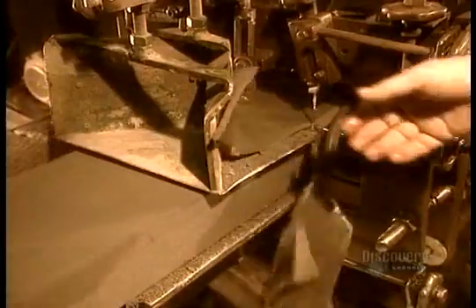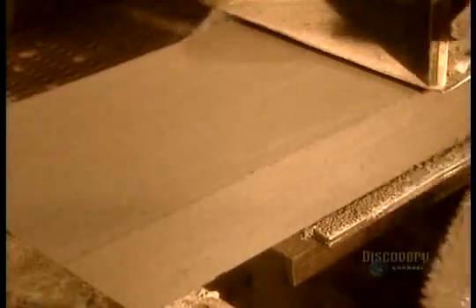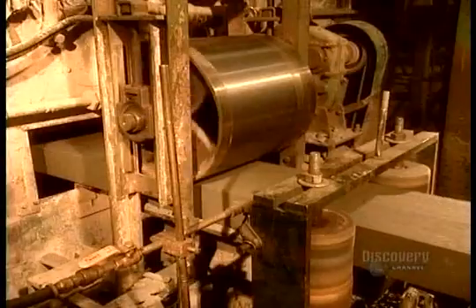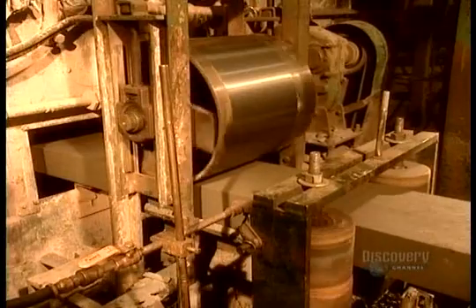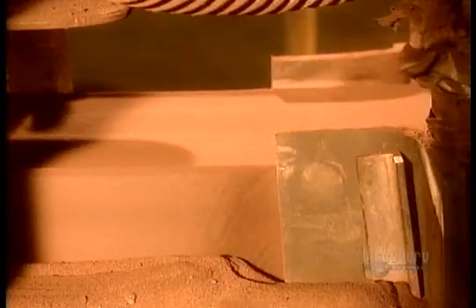At the same time, it shaves off the crustier top layer to expose what will become the face of the brick. If this grey shale mixture is fired as is, it'll naturally produce a red brick. To engineer a different colour, they coat the slug in sand mixed with an oxide mineral such as zinc or iron.